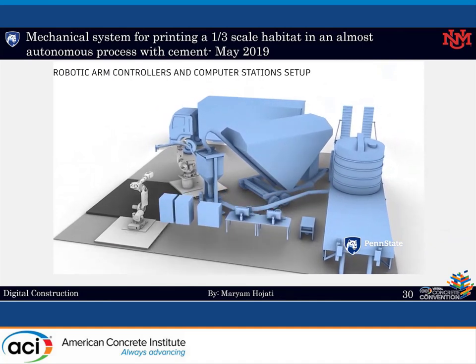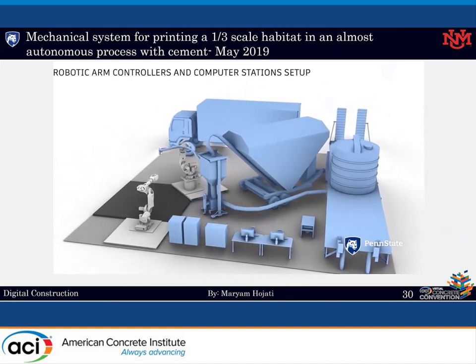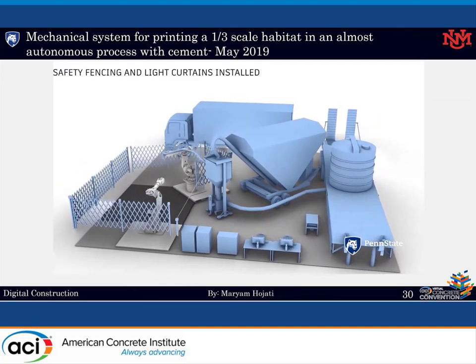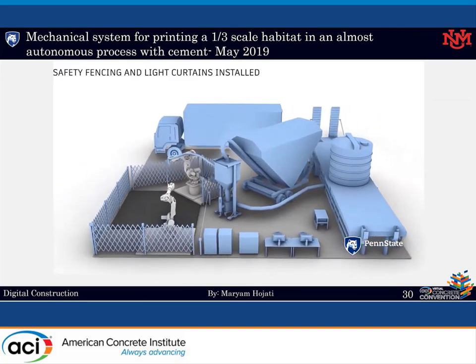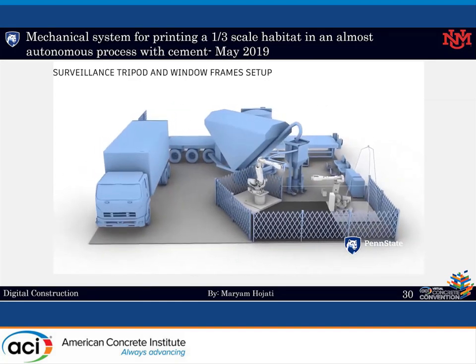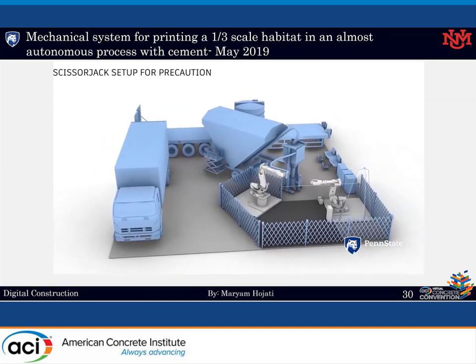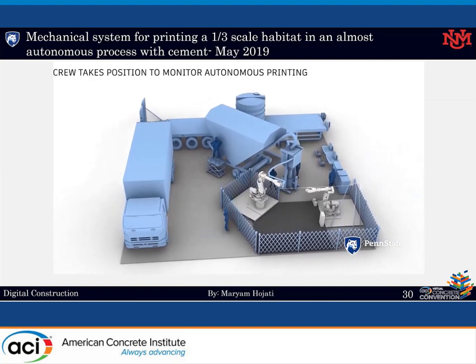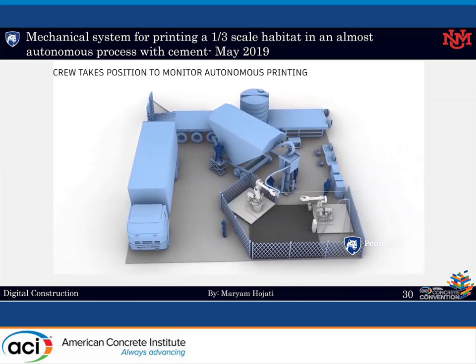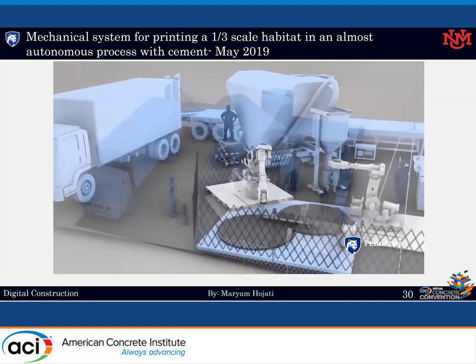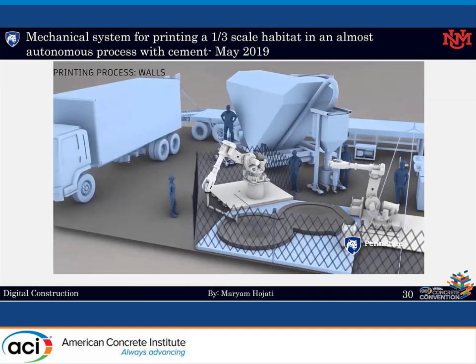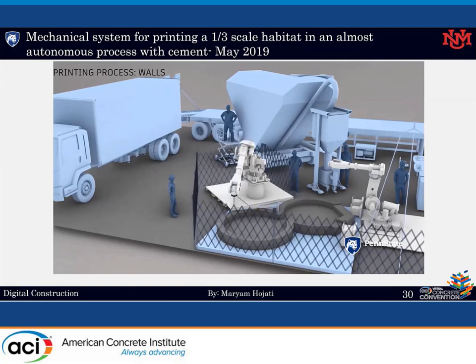We needed a 1,000 liter capacity water tank and water pump, a large silo for feeding the dry mix into the smaller silo, and a small silo for feeding the dry mix into the mixer. We had a conveyor belt to transport the dry mix between the silos and also to take the dry mix from the small silo to the mixer. Mixer and pump, which is a machine for mixing the dry mix with water and extruding the material.